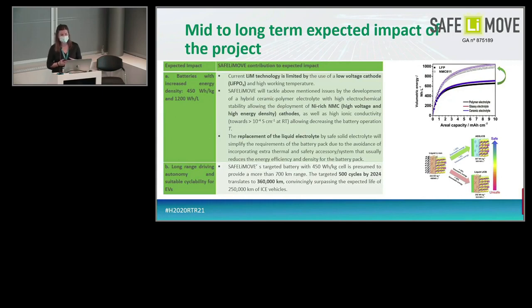So finally, if we focus on the impact that we foresee from this project, we can divide this in five main pillars, where we have the energy density, the long-range driving autonomy, the safety, cost, and finally the European value chain. So if we go to the first point, the energy density, currently lithium metal technology is limited to the use of low voltage cathodes, let's say LFP, and also to the need to work at high temperatures, around 80 to 70 degrees, mainly because of the semicrystalline properties of the polymers that are used.